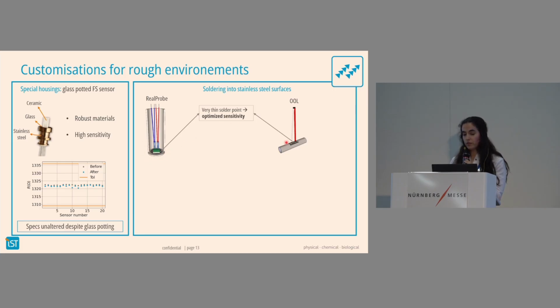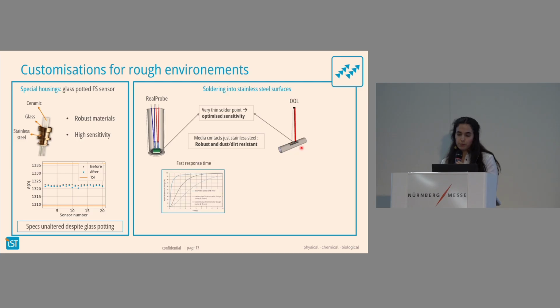And here is a flow sensor because we have a temperature sensor and a heater. The key here is to do this soldering point as small as possible or as thin as possible to not compromise the sensitivity. And what is very good about this solution is that the media just is in contact with the stainless steel, which means a very robust and dirt-resistant solution.